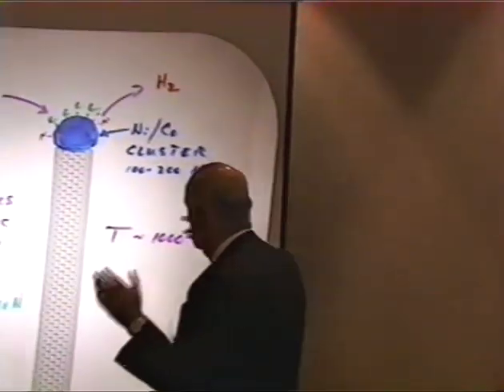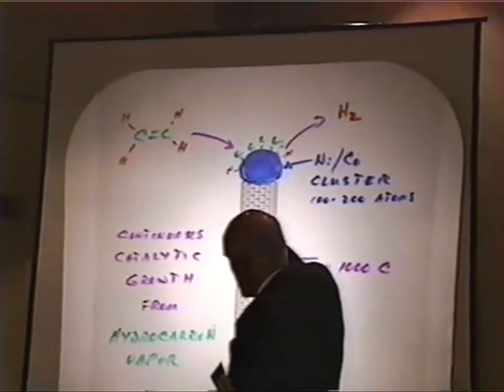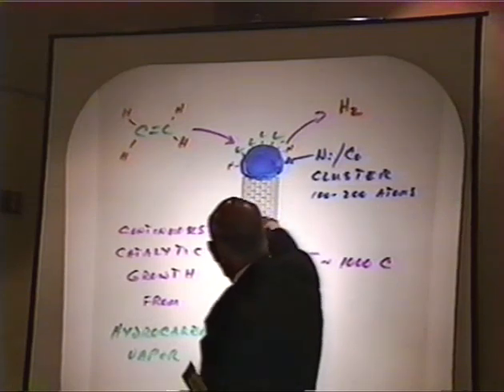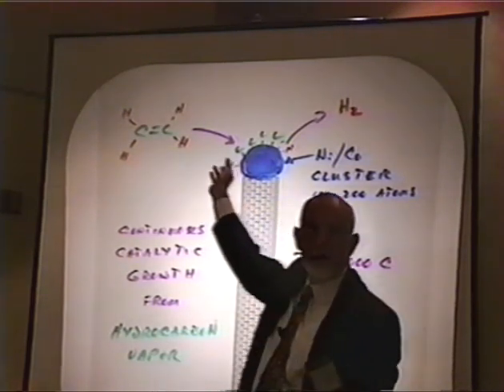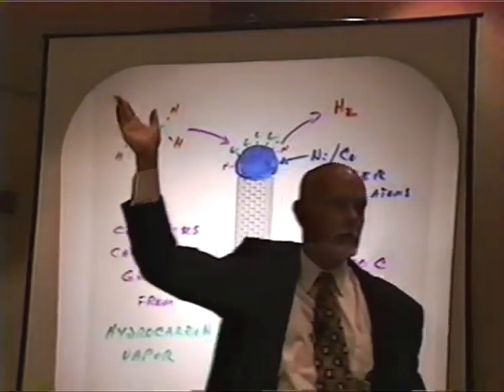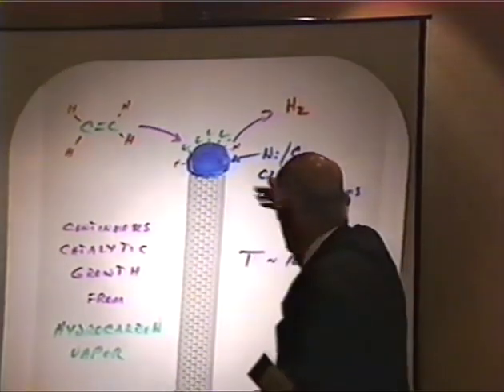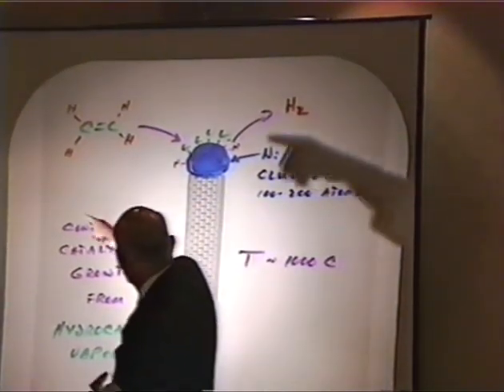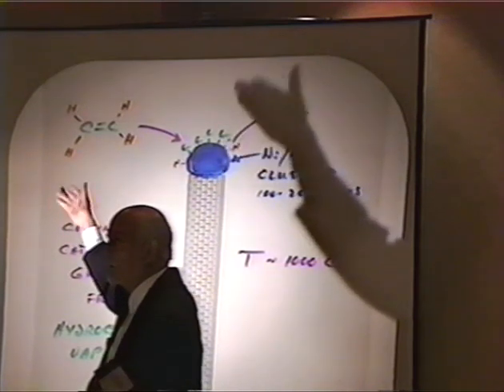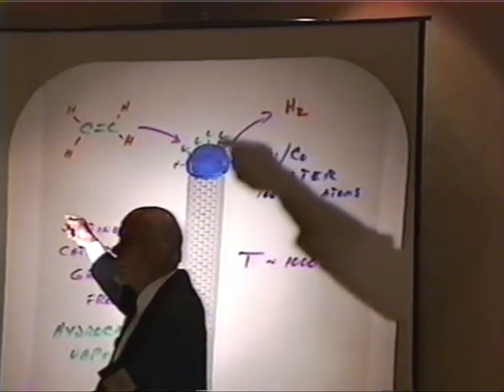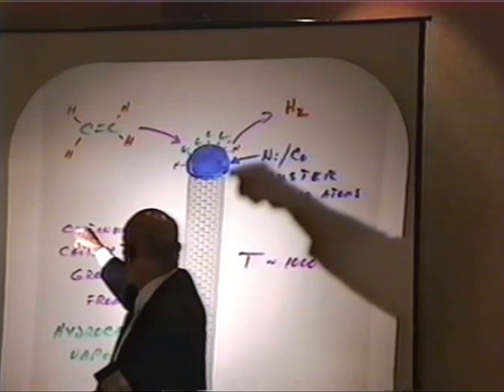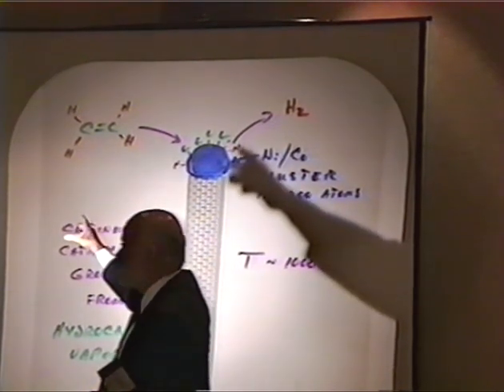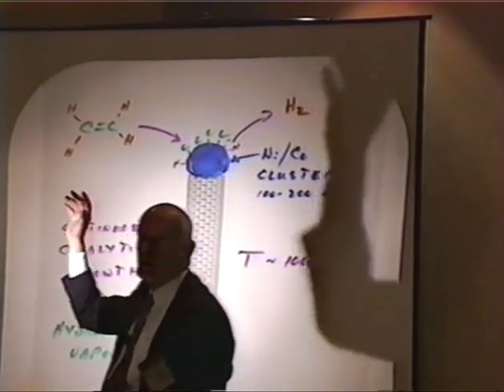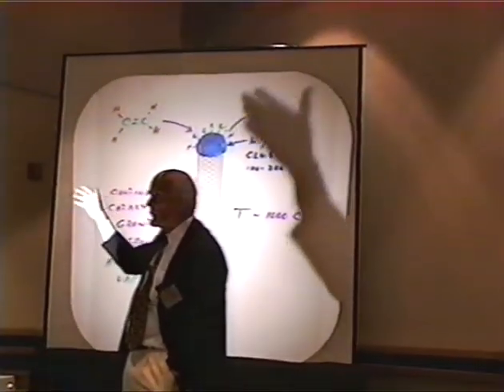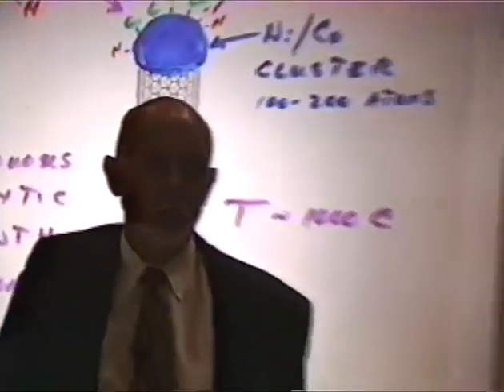So ethylene, for example, if it comes up to this thing, will dissociatively chemisorb. The hydrogens will go off at these temperatures as H2, driven by the entropy of H2 in the gas phase, leaving carbons behind on the surface. Without enough hydrogens to form a volatile molecule, they're sunk. They have no place else to go. They've got to stay there. And it turns out that these transition metals at these temperatures are effectively solvents for carbon, just like water is a solvent for sugar.